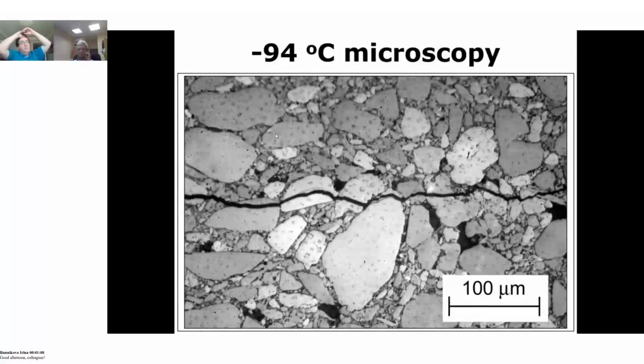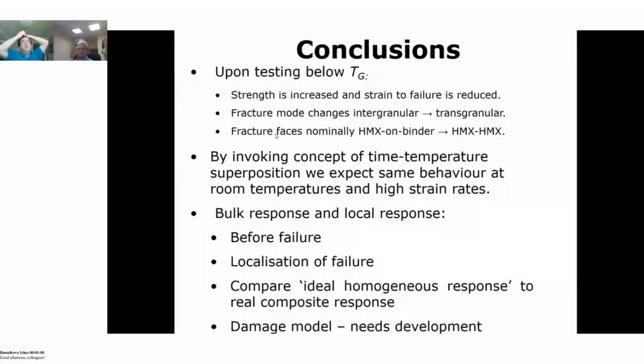So this is why we use in our studies a kind of homogeneous style of model using time-temperature superposition for the polymer bonded systems in the region where the system's undergoing bulk deformation, bulk motion, and we can get a very good agreement across strain rates. However, when damage starts occurring, we do get that very local response, that localization of failure.